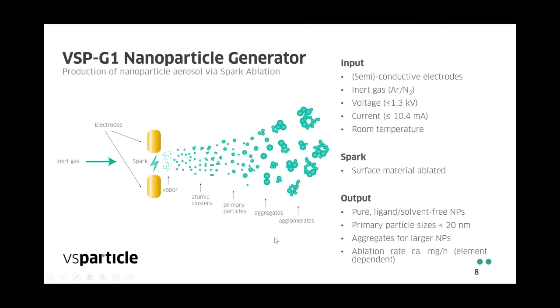Overall, the ablation rate is within the range of milligrams per hour, but this really depends on which element your electrodes are made out of, varying between a couple of milligrams per hour to tens of milligrams per hour.